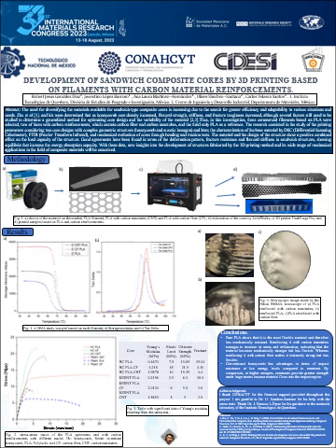Second one, the conventional honeycomb has an advantage in terms of impact resistance at low energy levels compared to reentrants. By comparison, at higher energies, reentrants provide greater strength under large strains because material flows into the impact region.